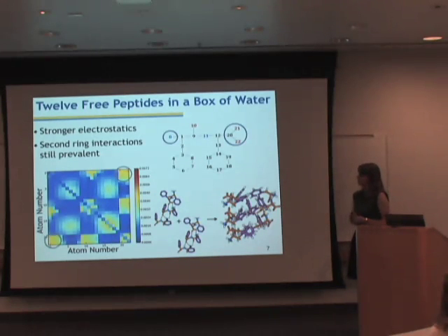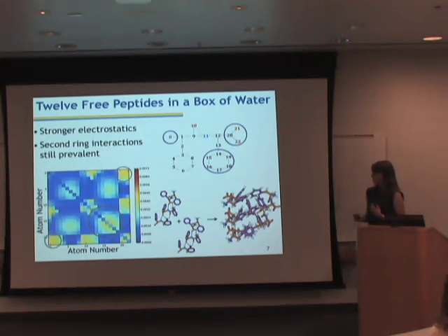the red dotted lines here. While it's no longer the most prominent interaction, we also see a relatively strong amount of interaction between these second rings, as we saw in the crystal structure. When we looked for snapshots representing this behavior in a video of a simulation, we found that these ring interactions became more prominent as larger aggregates formed, as shown in this cluster of 6 peptides here, where the side chains are these purple groups coming together.